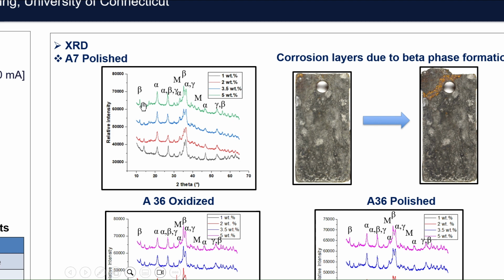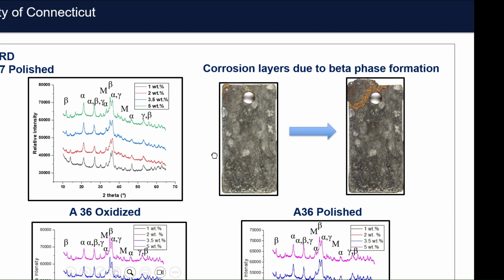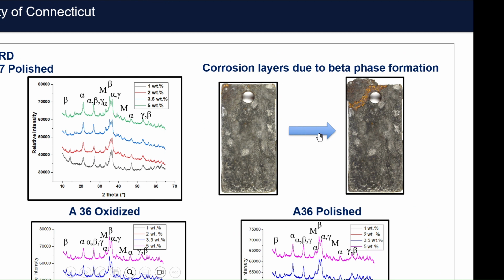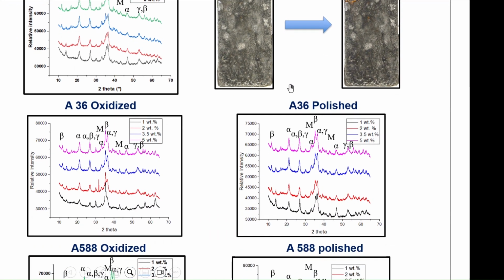Beta formation is really dangerous for the bridge performance, because of the reason explained through these figures. When the beta is formed at the interface, the corrosion products will spill off in the form of layers like this. Because of this, the product that is formed is no longer a protective product, and that will hinder the corrosion performance of the steel without forming a protective layer. So the presence of beta is not at all desirable, since it hampers the very good surface properties.